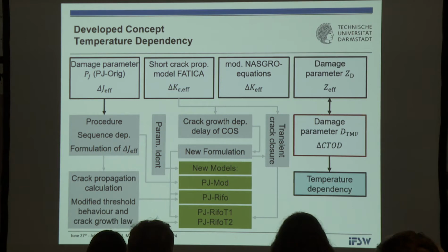This temperature, having different temperatures for different ranges or so, will cause another sequence effect. And taking this into account, we rely very much on the results of our research partners. Their postulate and hypothesis is that if you have a crack tip opening displacement, no matter what temperature is actually present in your material, you will have the same amount of crack advance. So the crack advance expressed in terms of the delta CTOD and the crack growth rate is independent from temperature. And we took that assumption, and this leads us, where we are going to the delta J integral, to the necessity that we have to readjust our crack growth rate equations, because the yield stress or cyclic yield stress relating these both quantities together is of course temperature dependent.